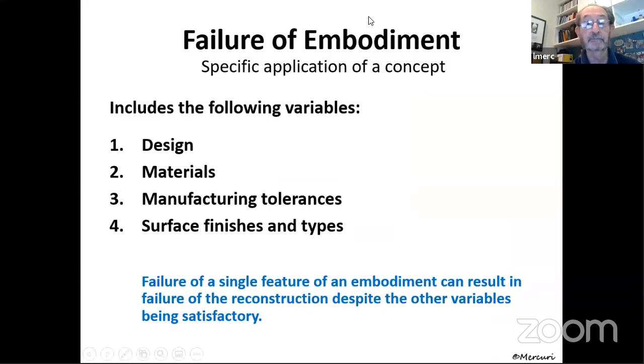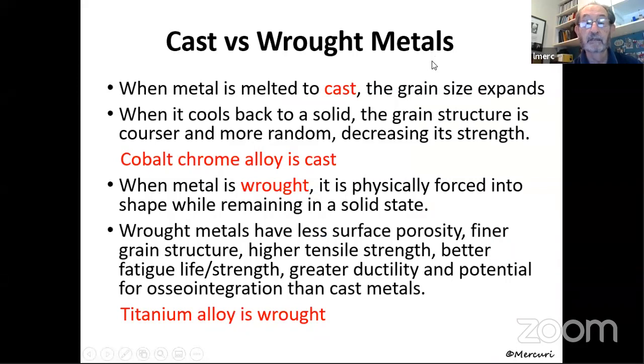So let's skip to embodiment. So we had the bad ideas. Now we've got the bad designs, the bad materials, the bad manufacturing. And so we're dealing here with metals. And I have to give you a quick course in metals because you have to understand the difference between a cast device where the grain size, that the material is melted so that the grains expand. And as the material cools, the grain structure changes. It shrinks down. Cobalt chrome is a cast alloy as opposed to titanium.